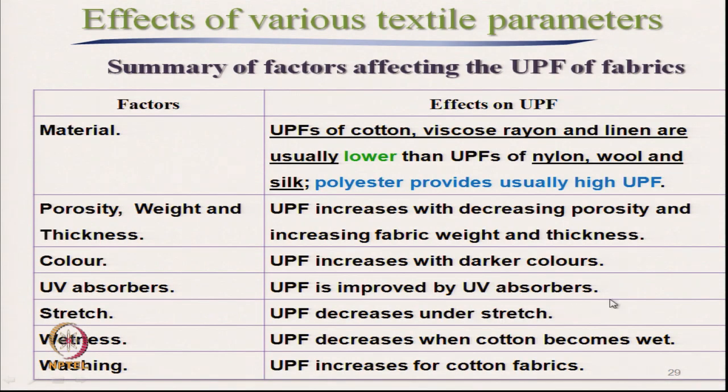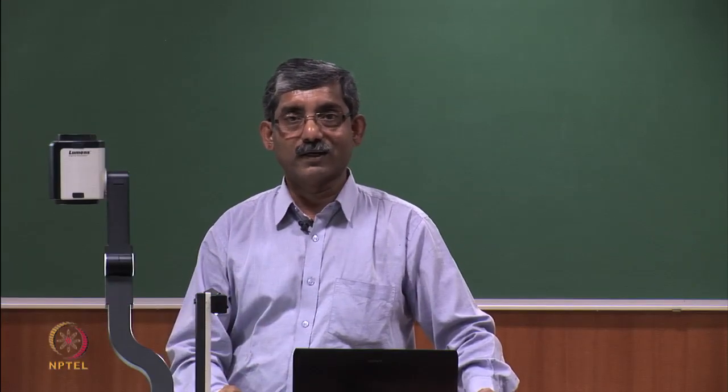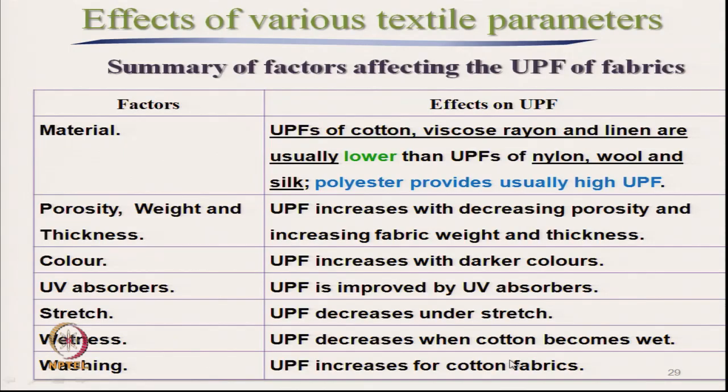If we increase the UV absorber, there are different UV absorbers available, so that will improve the UPF value. Increasing stretch will decrease UPF value, because if we stretch a fabric, that will create larger pores and UV ray will penetrate through that. Okay. UPF decreases with the wetness of fabric. So, when the fabric is wet, the UPF decreases.